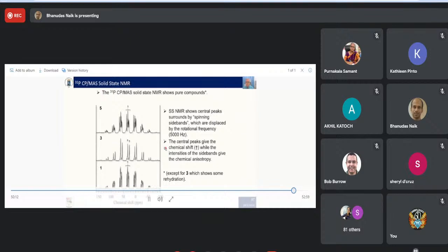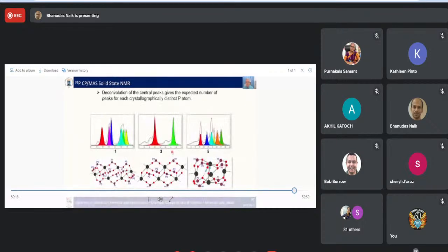So it has a little bit of rehydration here on the side. You see the little peaks on the side here, and we can expand those a little bit. You can see that we have six different phosphorus ligands, and you can see 1, 2, 3, 4, 5, 6 different chemical shift peaks for the phosphorus here. You always have a small amount of extra impurity on this side, which I have no idea what